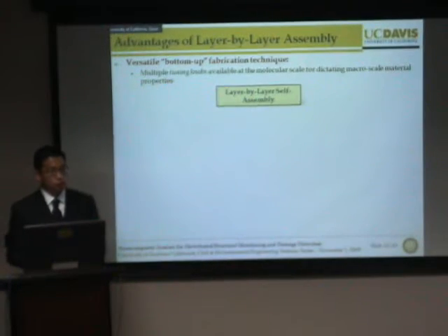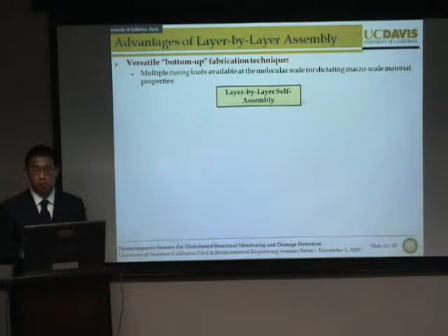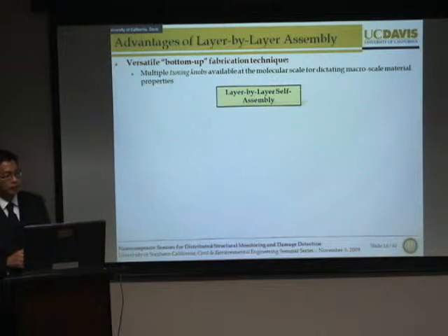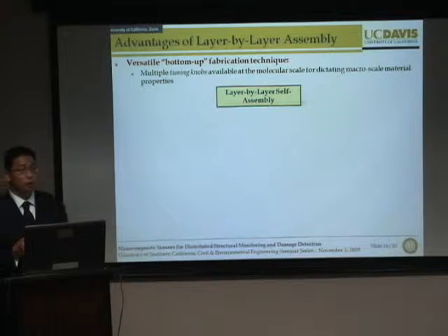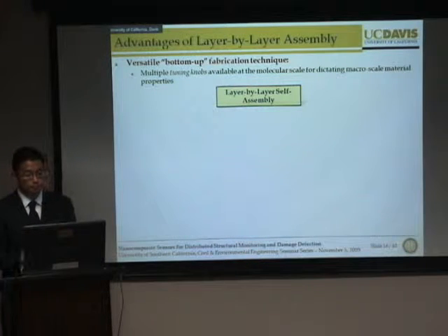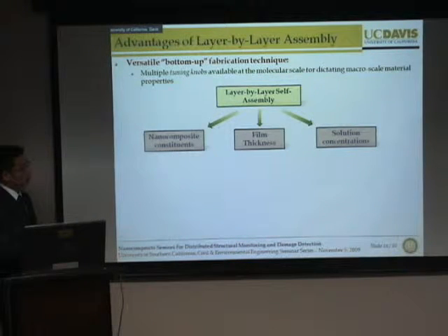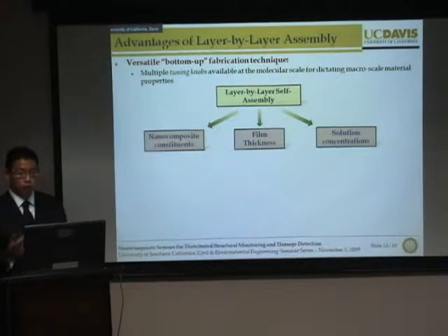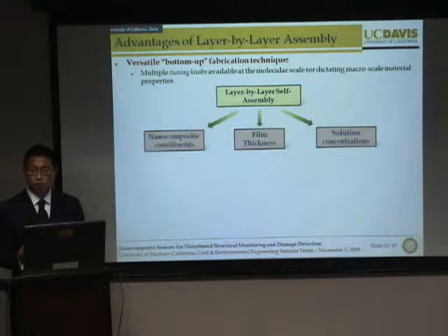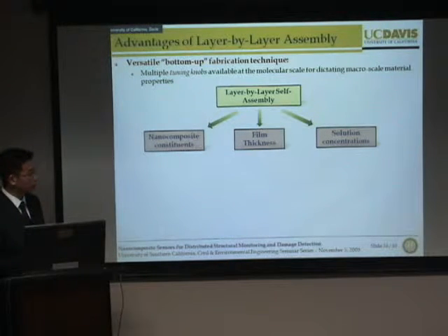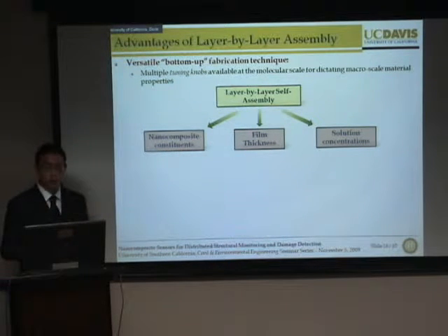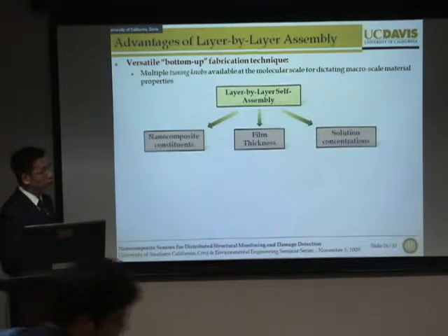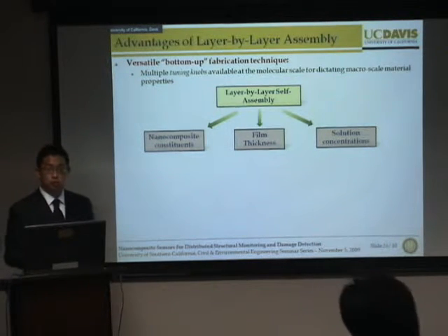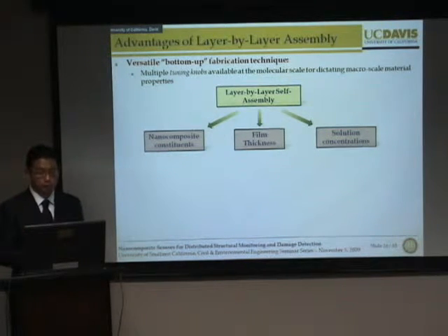But in addition to being able to control the material at smaller length scales, the layer-by-layer technique is actually an inherently very versatile thin film fabrication technique. As you can imagine, we can easily control different carbon nanotube constituents by varying the type of solutions that we use. We can control the number of layers to vary thin film thickness for different applications. And we can even vary the solution concentrations to control how much of the material is deposited.